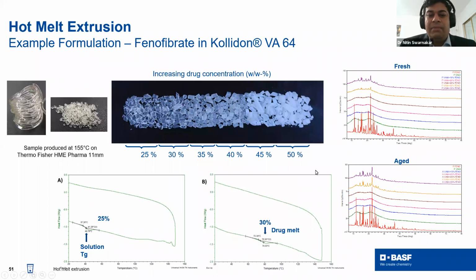But when you increase the amount of drug, you can see melting. It means at 30% it is becoming more crystalline in nature. And if you do the same experiment with XRD, you can see the crystallinity of the drug. But this is the polymer itself, and then we have different levels. At higher levels, you can see there is more crystal formation. But here, there is no crystal formation. When you store them at 25 degrees centigrade and 75% RH, or maybe your stability condition, you can see the crystallinity change. If the crystallinity changes, it means the overall ratio is not established. And if it is stable, then we can say the overall formulation is stable.